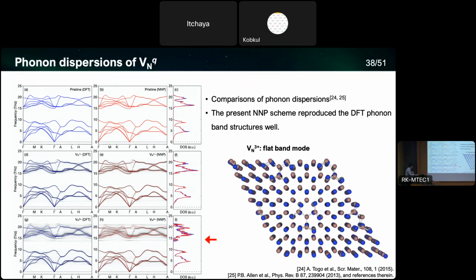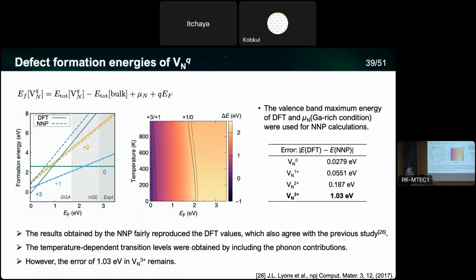And these predictions are in quite good agreement between the two methods. And then next is to verify the prediction performance of energies through the vacancy formation energy. So these are the equations, and what we get is this graph. The solid lines are the DFT, and NNP are indicated by the dotted lines. So for 4 different charge states, except for the +3 charge state, we get quite good predictions. And the errors are tabulated in this table.